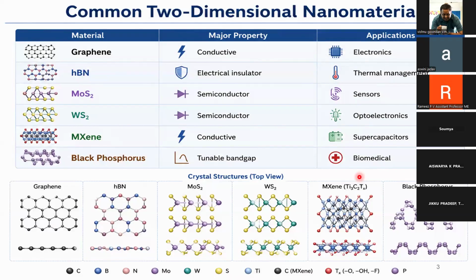So these are the commonly used two-dimensional nanomaterials, which have been employed for several research purposes or applications. You can see graphene, HBN, MoS2, molybdenum disulfide, then tungsten disulfide, MXene, and black phosphorus. And you can see that each nanoparticle has different properties. Like graphene is a wonderful nanoparticle, which has better thermal as well as electrical properties. So it is mostly utilized for applications like electronics, whereas HBN, where my research was